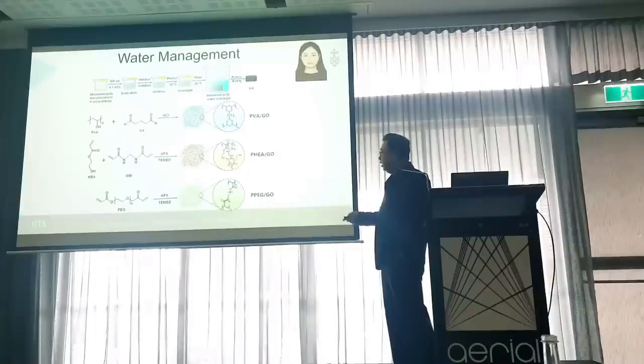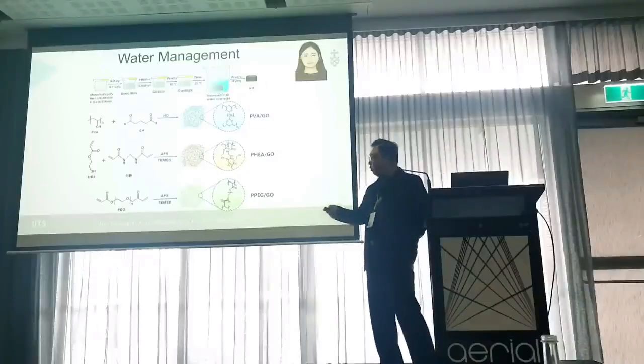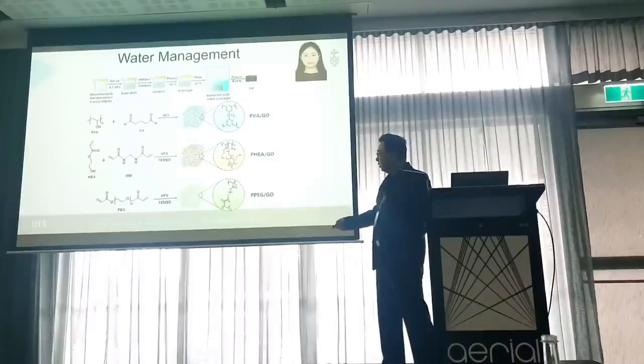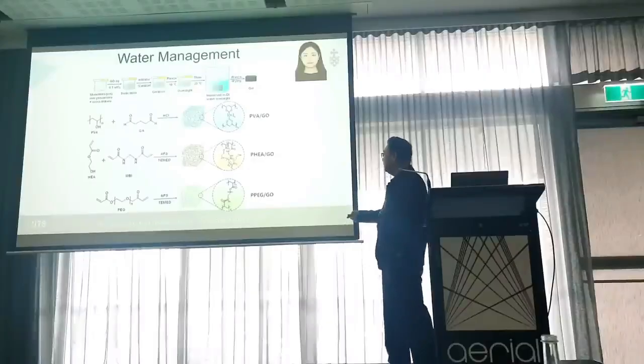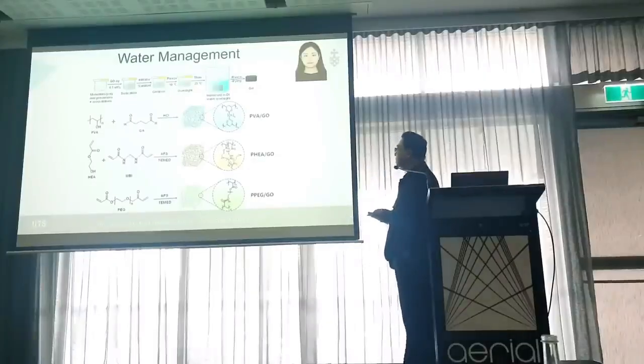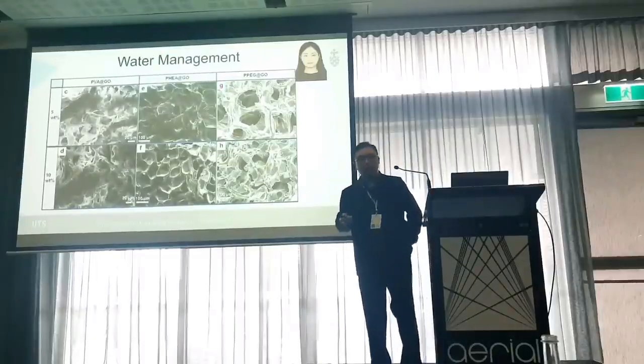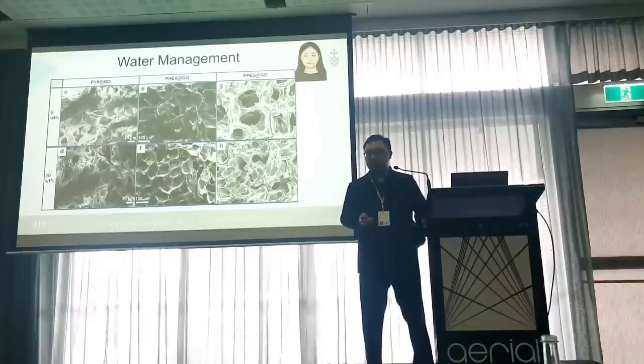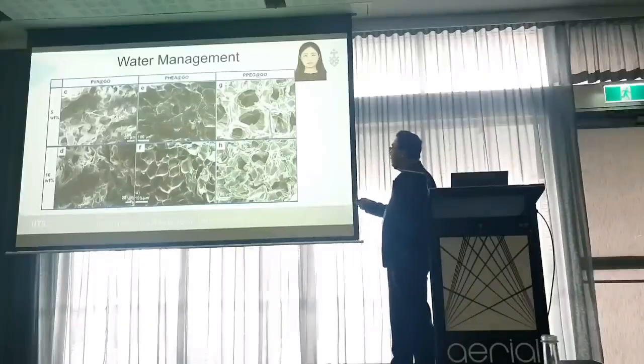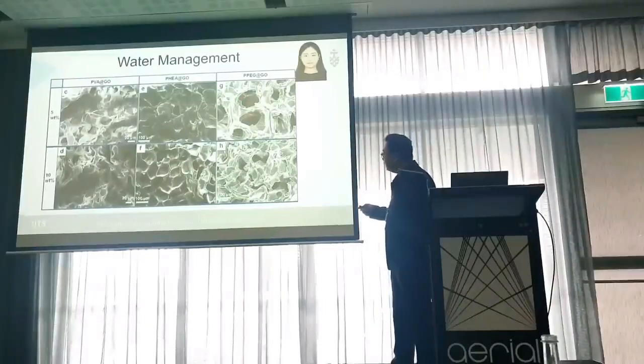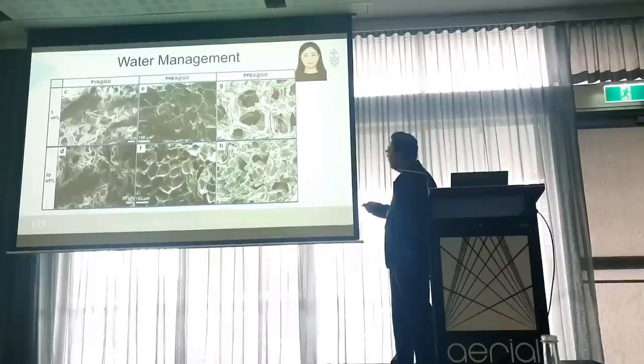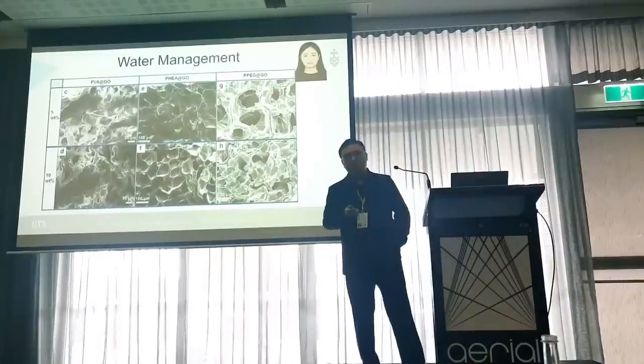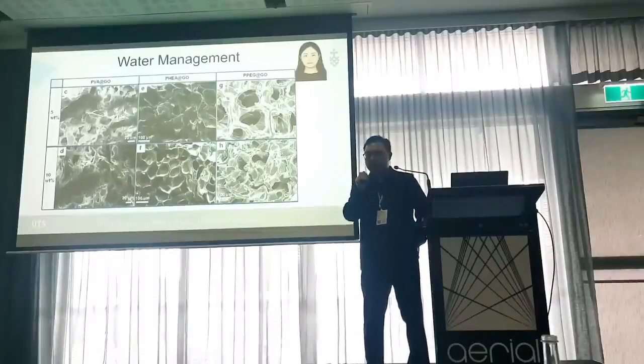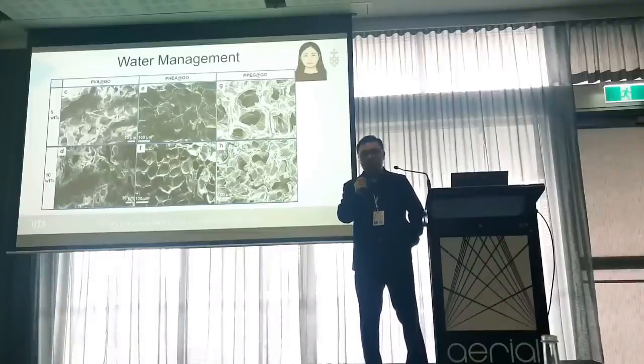In her study, we use different polymer precursors, including PVA, polyvinyl alcohol, or PEG, as different polymer precursors to construct the hydrogel materials. Accordingly, we obtain these 3 composite hydrogel materials. We first characterize the morphology of these hydrogel materials, as you can see from the SEM image. All the hydrogels have micropore structure. However, interestingly, we find that the PEG composite hydrogel has a relatively larger pore size, and all the pores are interconnected, as you can see from this image. So this structure is expected to show faster water transport.